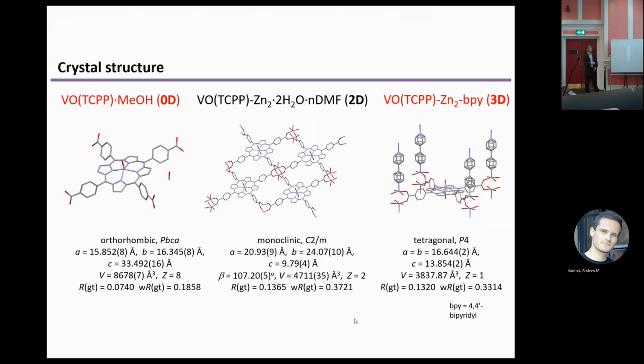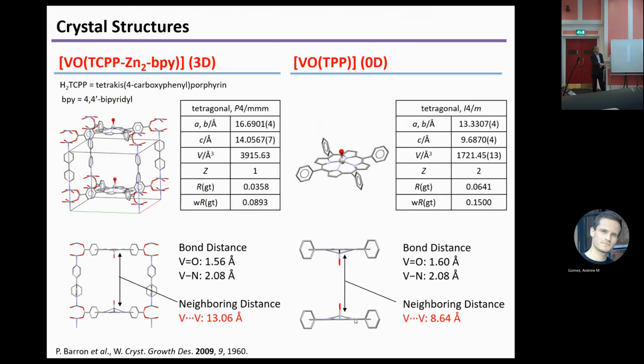For this purpose, my students took the tetracarboxyl phenyl oxyvanadium TPP, this zero-dimensional starting material, added the zinc ion to make a two-dimensional network, and added the bipyridine to make a three-dimensional MOF. I compare the zero-dimensional starting material and the final target three-dimensional MOF. We compare the crystal lattice. So this is the crystal structure, the vanadium distance. This is the zero-dimensional starting material. This is the three-dimensional MOF. So the vanadium distance is different.